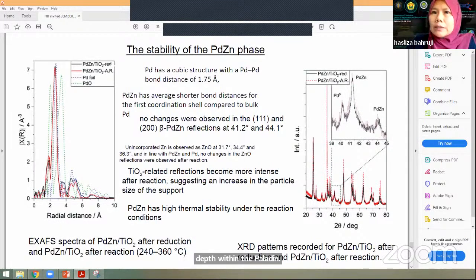So the black one is palladium zinc titanium that has been reduced, and the red one is palladium zinc titanium after reaction. And we can see that there is not much difference in terms of the coordination number of palladium metal. It tells us that there is no enlargement or growth of palladium zinc nanoparticles when we have reaction at low temperature. And then when we do the XRD analysis before and after reaction, it's basically quite similar. Palladium metal, we still see palladium metal, and then we still see as well palladium zinc alloy nanoparticles. And it tells us about the stability of the catalyst for reaction at high temperature and longer reaction. So it has high thermostability under reaction conditions.